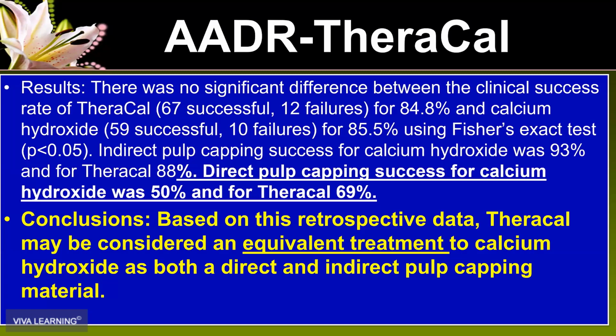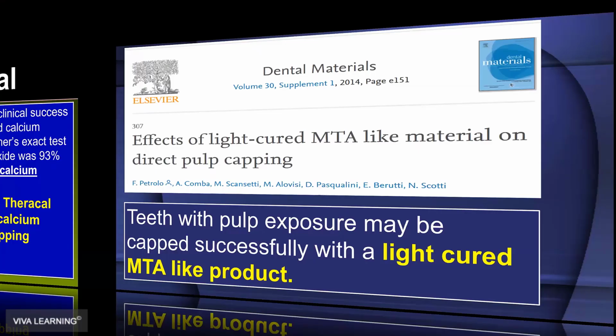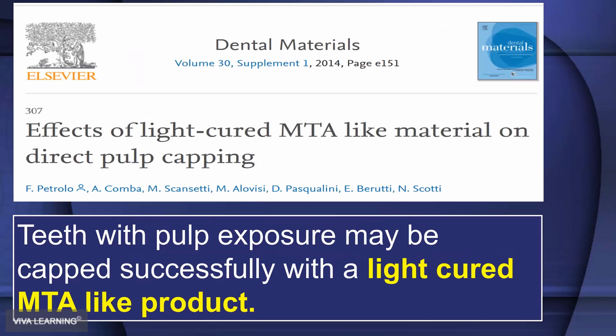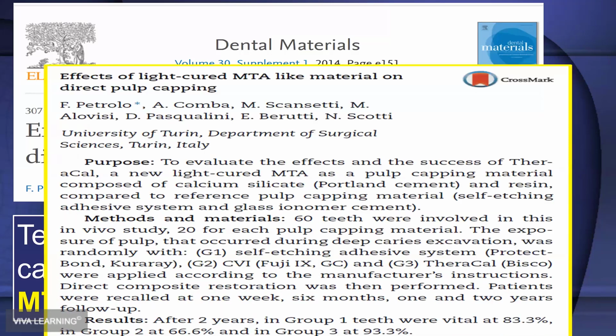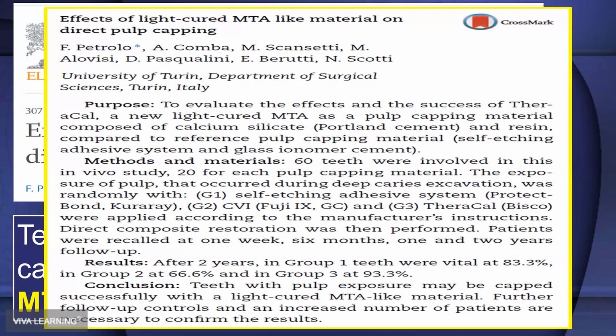There was a slightly higher indirect pulp capping success rate with calcium hydroxide than with TheraCal, but definitely TheraCal was as good, if not better, for direct pulp capping than Dycal. And of course, published in Dental Materials was this study that came out of Italy, and they looked at this light-cured MTA-like product, which was actually TheraCal, and they had 3 groups.